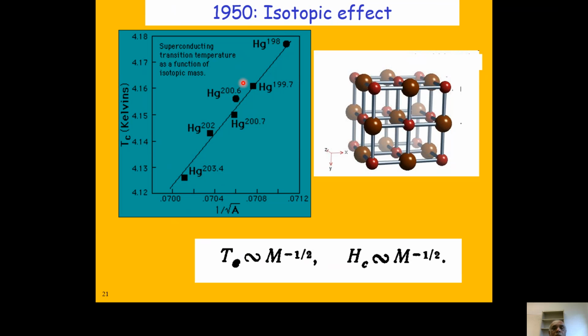So they have different Tc values, which change. We know mercury has a Tc around 4.15. But if you change your atomic mass by making isotopes, it actually changes from 4.12 to 4.18. So then if you look at atomic mass versus Tc, they are inversely proportional, but they found that Tc goes as 1 over square root of m.